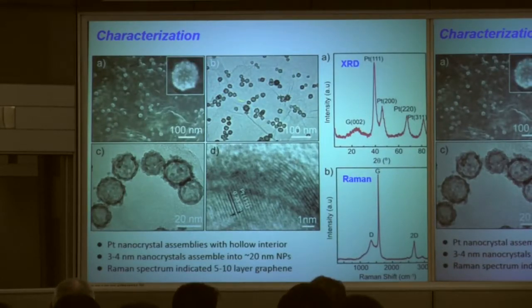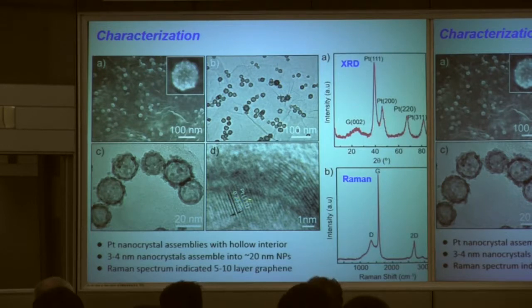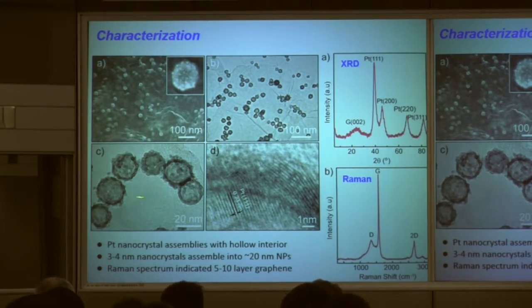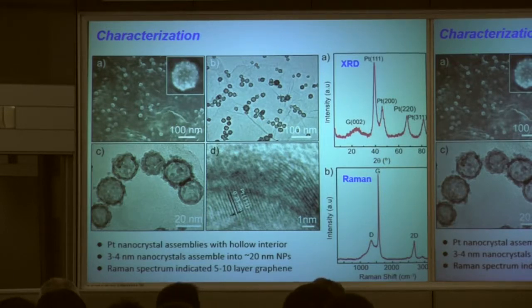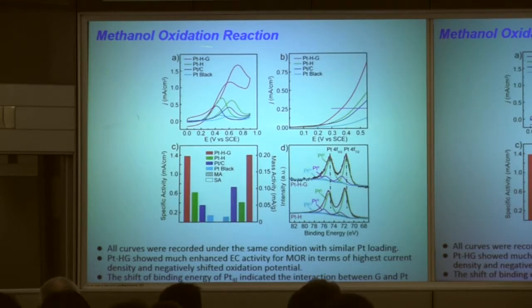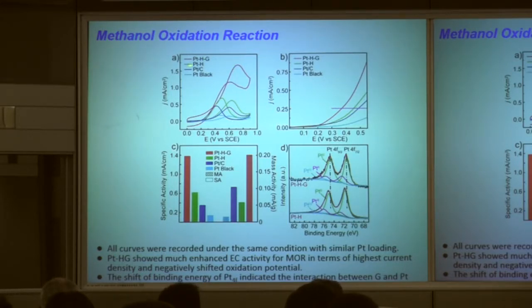Here is a high-resolution TEM image. You can see here is a single nanosphere, and here is a large area. On the surface, you can find the spacing distance is similar to the platinum-111 spacing. That means we can get a well-crystallized platinum-111 surface on graphene. We also demonstrate this nanosphere on graphene surface using Raman, showing the G-band and D-band results. We also measure the methanol oxidation reaction, and this new composite material has very high performance for this oxidation reaction. The details about the mechanism are still in progress.